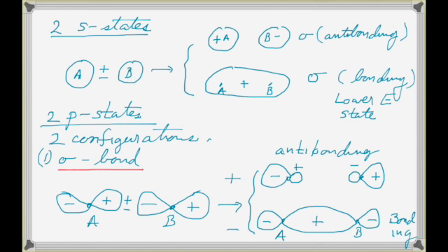And this would constitute, say, the LUMO, the lowest unoccupied molecular orbital, and then this would be the HOMO, the highest occupied molecular orbital. Usually, if there are pi bonds around, the pi bonds will serve that role, which we'll talk about in a minute. These kinds of bonds will also form in carbon nanotubes and graphene. They're not the ones that we usually worry about for electronics because they're pretty far away from the Fermi energy, and we'll talk about that in a second also.